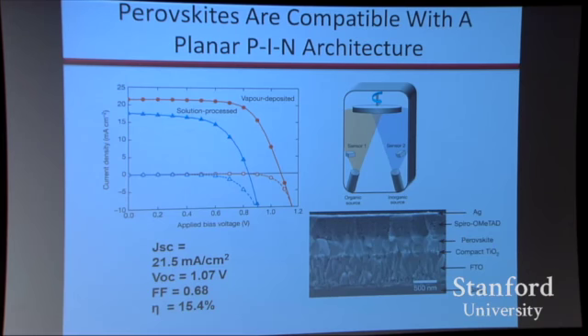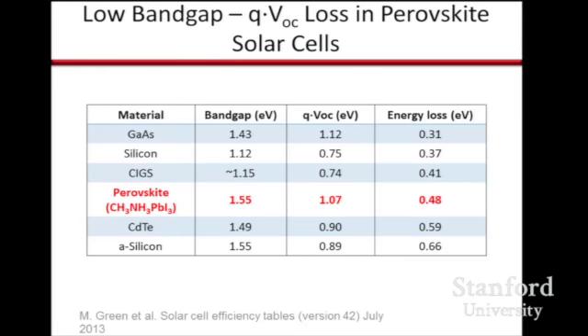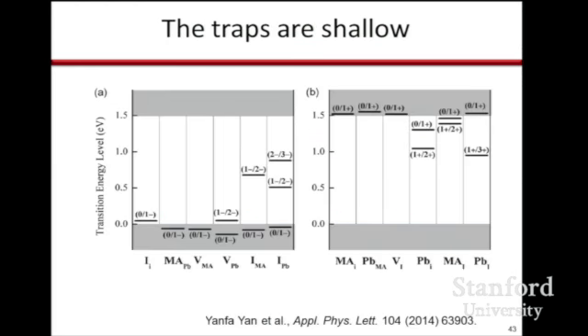And so here you realize that this is really very similar to CIGS or cadmium telluride. It's a polycrystalline semiconductor where there's very little recombination, even though there are a lot of grain boundaries in there. The voltages are very high for a polycrystalline material. And a paper just came out showing that the defects in this material give you trap states that are very, very shallow. They're right at the band edges. And that's probably why this material is so special.